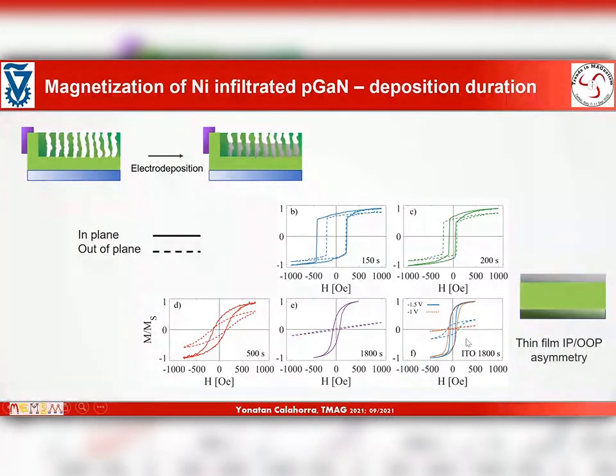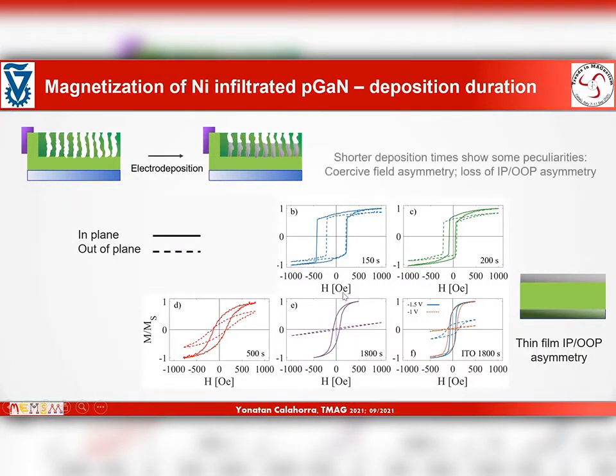embedded? So if we look at control samples deposited on ITO electrodes, we see a classic easy axis, hard axis behavior. This also happens in the thicker layer deposited on gallium nitride. And when we move on to the shortest deposition times we use for the larger pore samples, we actually see a very interesting response.